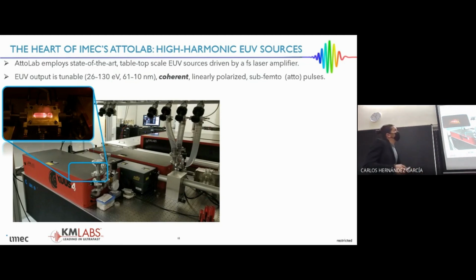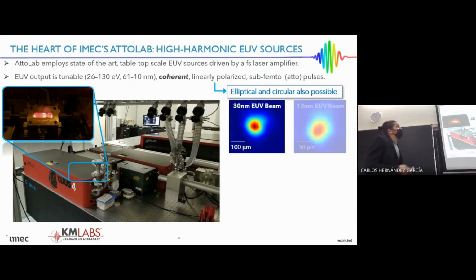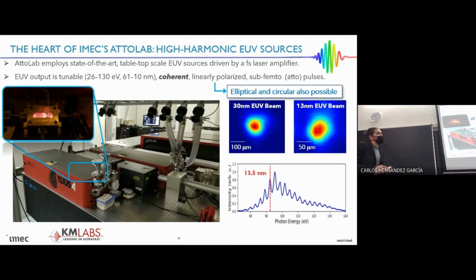We do this in 3 different gases: argon, neon, helium, and this gives us quite a broad tunability range for the EUV light, something on the order of 26 to 130 eV. Right now, we're set up for linear polarization, but we also have plans to do elliptical and circular, not just because it's fun, but because there's a lot of interesting dynamics to study, especially with spintronic materials. And we get quite nice beams out of this system. They're highly stable, they're focusable to small dimensions.